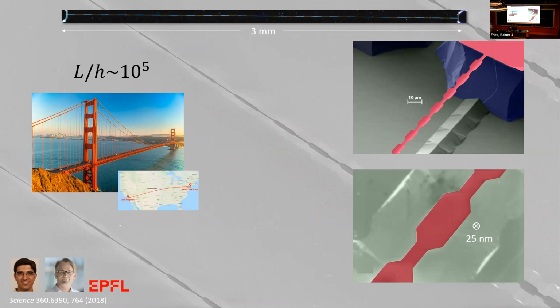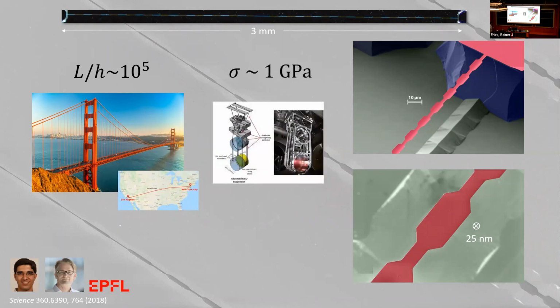Something which is really extreme at the macro scale, but quite possible actually using modern nanofabrication techniques. So another thing that you can't tell from this picture is that this device is under really high tensile stress. And the reason for that is this silicon nitride is deposited on silicon using a deposition process that occurs at 800 C. And when it cools down, the thermal mismatch between those two materials gives rise to a really large tensile stress, around 1 gigapascal.